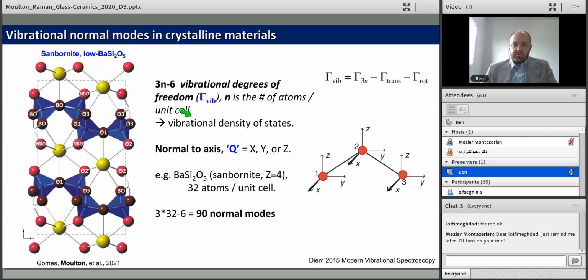So each of the atoms in the crystal structure can vibrate in 3 normal directions, the 3 Cartesian coordinates, x, y, z, for example. And if we do the math here, there are actually 4 compositional units in the unit cell of sanbornite. So that makes 8 times 4, 32 atoms in the unit cell depicted here. And if we multiply by 3 for the 3 Cartesian coordinates, minus the 6 pure translations and pure rotations, we end up with 90 vibrational modes. And Raman spectroscopy gives us access to some of these modes.